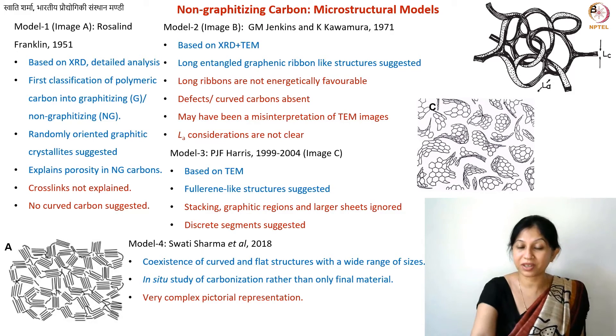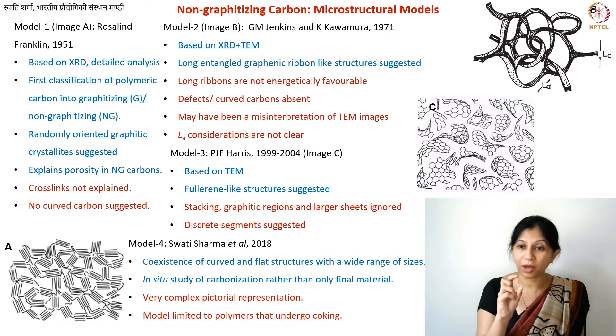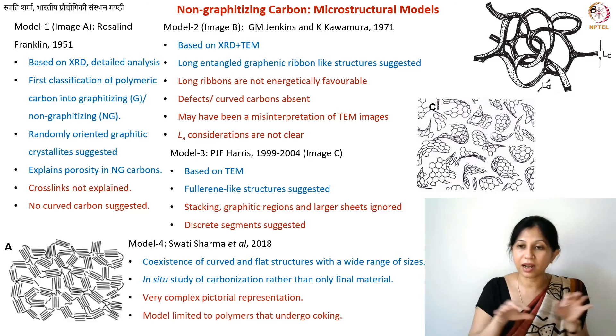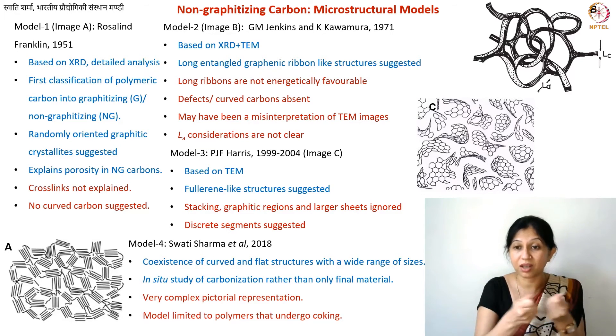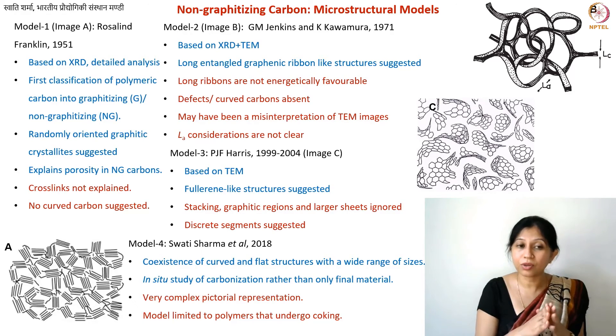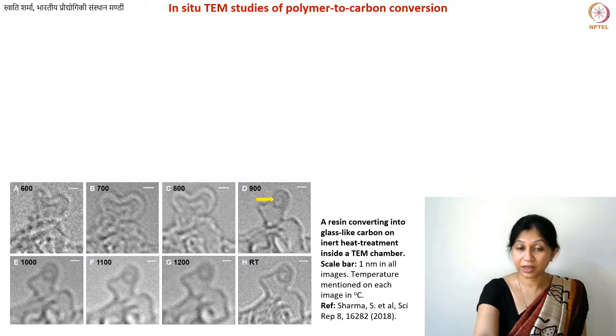The pictorial representation of this model is complicated to date. Another limitation is that we performed this in-situ study on one type of polymer that goes through a coking mechanism — where polymer flakes float, merge, join or separate because the material goes through a semi-solid phase during carbonization. We do not know if the same thing happens during charring. So currently this model is limited to non-graphitizing carbons obtained by the coking process.